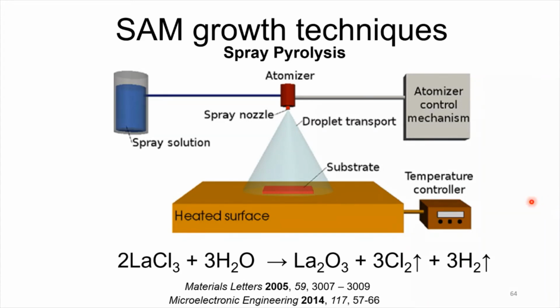The moment it comes into contact, these are very small droplets, so the water really evaporates very fast and evolves into chlorine gas and hydrogen gas, but it leaves behind a lanthanum, or in our case, a holmium oxide film. This is a very thin film that then we can use to build the MOF around it.